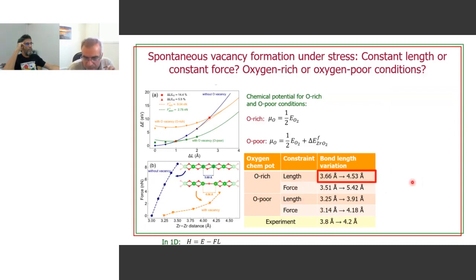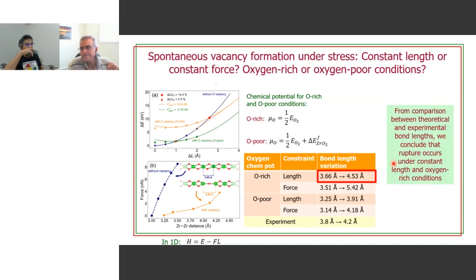And just by comparing this number, we conclude that likely this is the closest match to the experimental results. So likely the process of spontaneous vacancy formation is happening at oxygen-rich conditions and with a constraint of pulling the two wires at constant length, at different steps of constant length. So the system equilibrates at a certain length, and then you move the two walls apart again and let the system equilibrate, and so on and so forth. So this is the final conclusion of this theoretical analysis. From this comparison, we conclude this rupture occurs at constant length and oxygen-rich conditions.